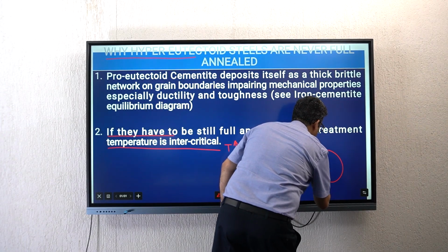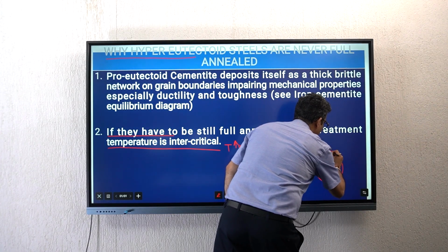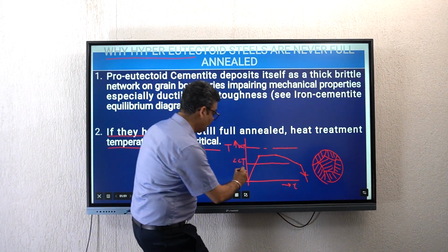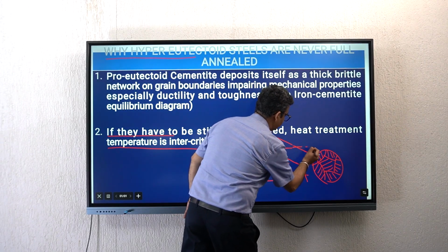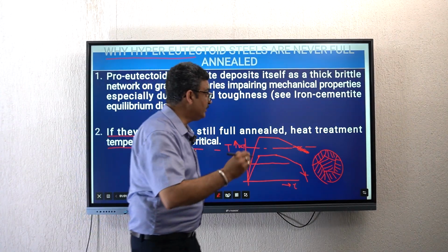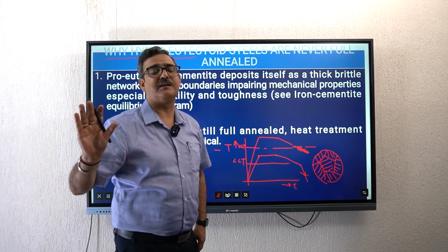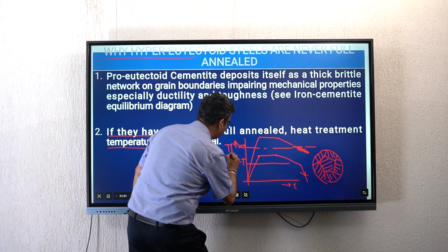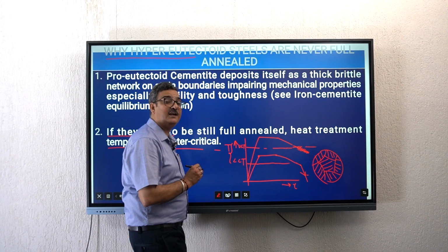इसके बाद जो आपको माइक्रोस्ट्रक्चर मिलेगा, आई हैव शोन ऑन द नेक्स्ट स्लाइड ऑल्सो, बट यू विल सी दैट फाइन ग्रेन्स ऑफ ऑस्टेनाइट आर देयर, perlite got formed because of austenite transformation at the lower critical temperature, and this cementite which used to come on the grain boundaries, if you were cooling from here like this, अगर आप यहां से कूलिंग करेंगे, ये अपर क्रिटिकल, यहां जो ट्रांसफॉर्मेशन होगी सारा आपका प्रोयूटेक्टॉइड सीमेंटाइट ग्रेन बाउंड्रीज पर आ जाएगा. तो हम नहीं कर रहे इसको, अपर क्रिटिकल टेम्परेचर से ऊपर नहीं लेके जा रहे, हम लोअर क्रिटिकल टेम्परेचर से ऊपर जा रहे हैं, अपर से नीचे हैं. तो कौन सी तरह की अनीलिंग हुई? इंटर क्रिटिकल अनीलिंग, पार्शियल अनीलिंग, इनकम्प्लीट अनीलिंग.